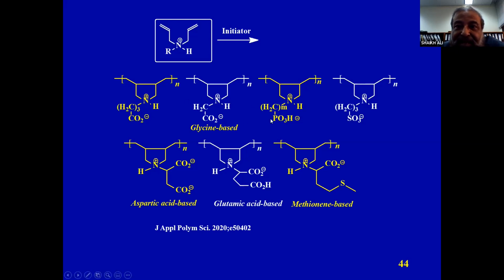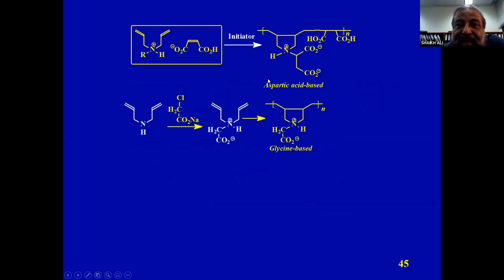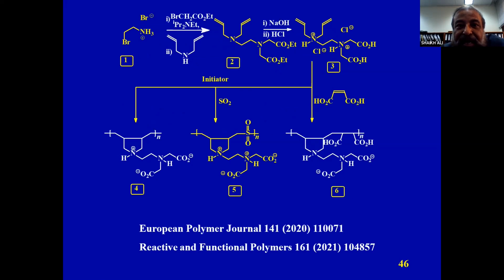So we made, you can see here, numerous antiscalants, glycine based, and this here aspartic acid based, glutamic acid based, methionine based, and we have made aspartic acid based, glycine based polymers, low molecular weight, and we have made another kind. We introduced this number 5 as a polymer in the literature, the first example of bis-zwitterionic motifs.